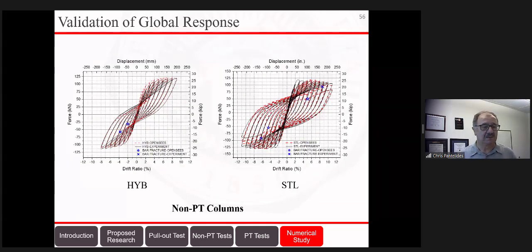So what is the result? You can see this is for the non-post-tension columns. For the hybrid column on the left and the steel column on the right, we predict successfully the performance within, say, an error of 3% up to 3% drift, and we have an error of 8% beyond that. And then the model stops at around 9%, where the GFRP fractures.